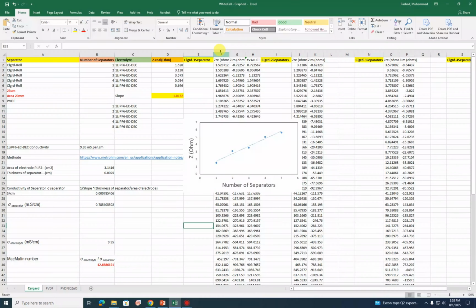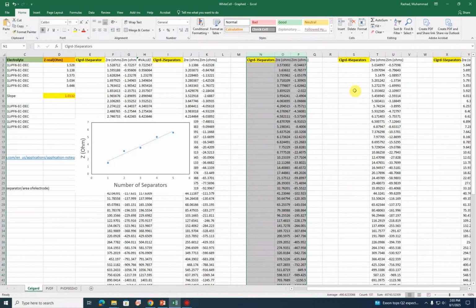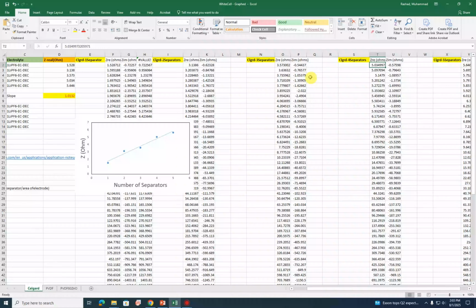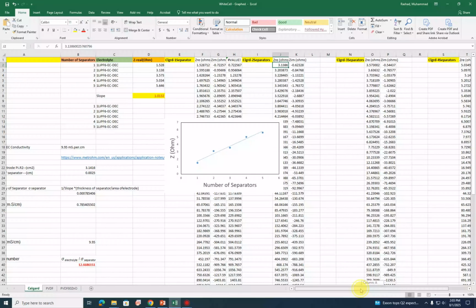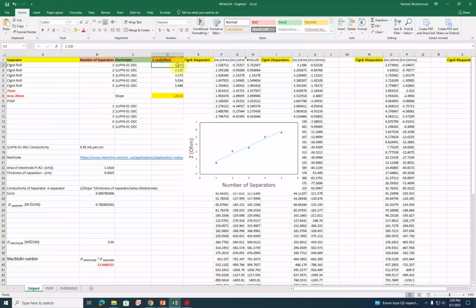You can see this is the Celgard when I use the separator 1. When I increase the number of separator to 2, then this is the resistance. Similarly, total number of 3 separator, 4 separator, and 5 separator. And this value gives us the resistance of the separators, either it's 1, 2, or 3. Then I use these real resistance versus number of separators and draw a graph and calculated the slope.